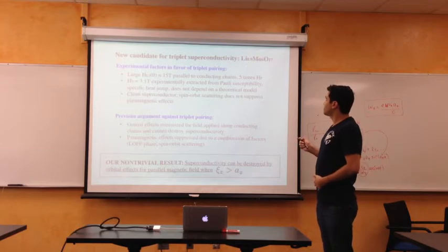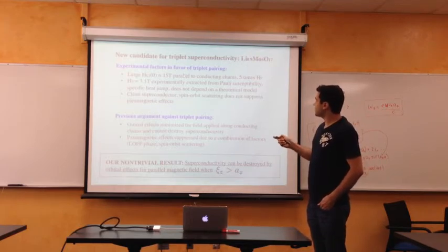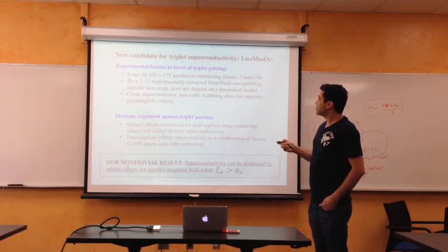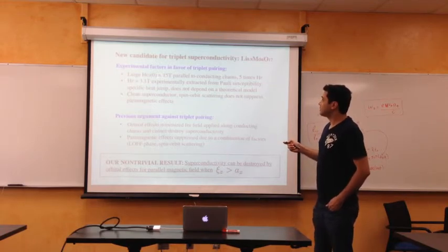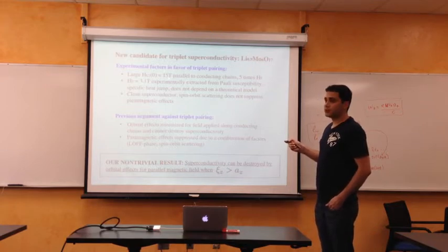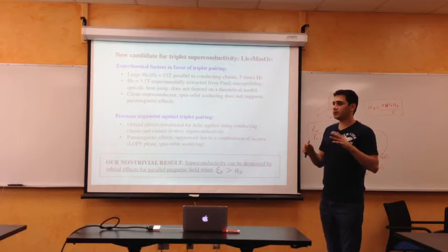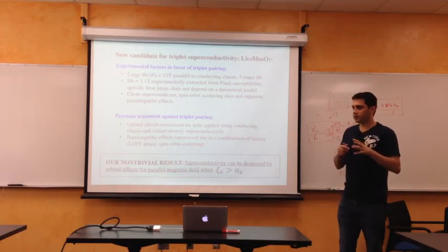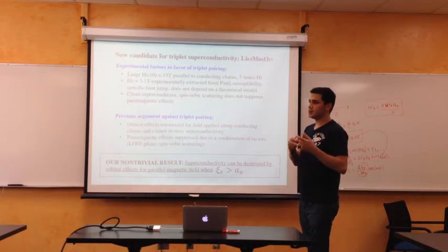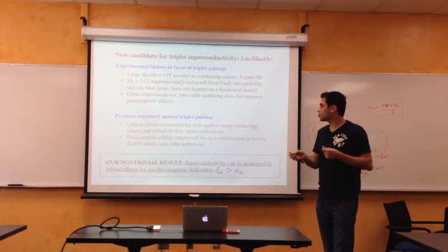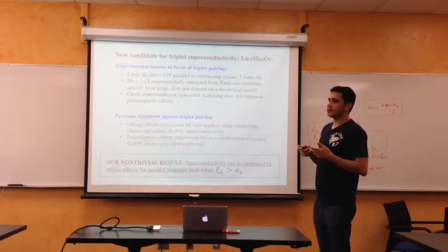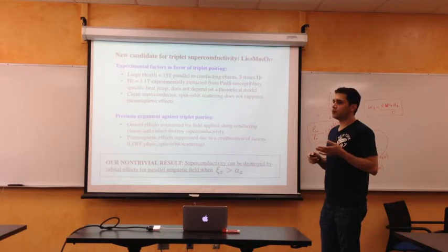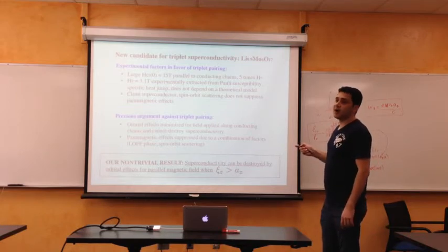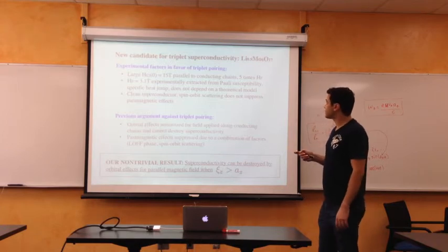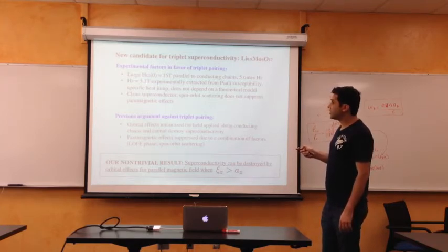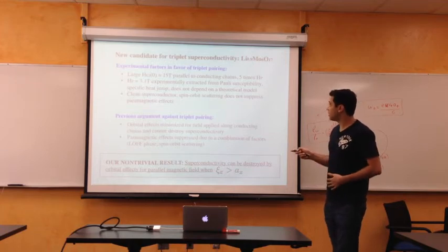So we propose a new candidate for triplet superconductivity. This is a summary of the facts in favor. The most important one is that we really cannot account for such a large critical magnetic field, even if we somehow magically combine all the factors such as spin orbit coupling, maybe some electron-phonon coupling in a strong limit. The renormalized values would bump up HC2 maybe to twice the value, but not 5 times the value of 15 Tesla. And again, the paramagnetic limit has been experimentally determined - it does not depend on any kind of theoretical model.